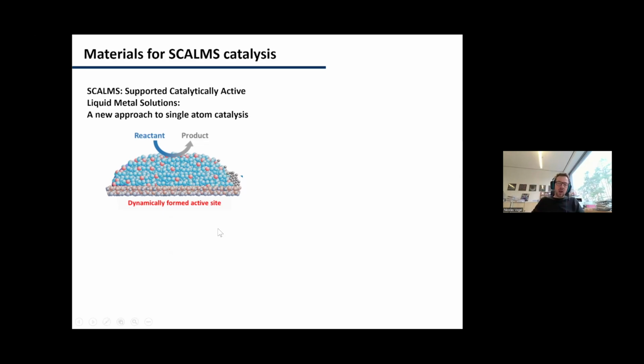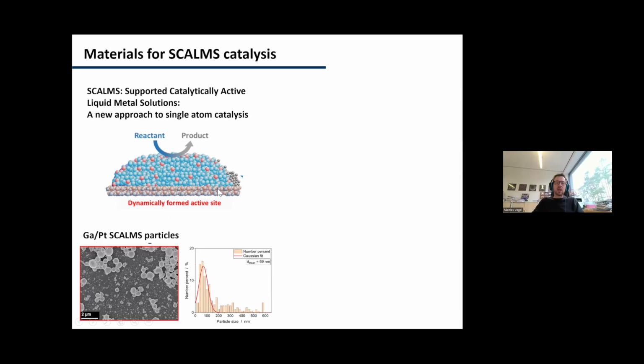So it's a fairly attractive system that a lot of people, at least here in Erlangen, are currently playing around with, but there is a key difference to normal heterogeneous catalysis. And that is that the particle size of such systems is much larger than what catalyst people are typically used to. And this is what you see here. The way this is prepared is often by ultrasonication or by comminution. And what comes out is something around 100 nanometers in particle size. And that means that any conventional catalyst support simply has pores that are way too small to accommodate the particles.